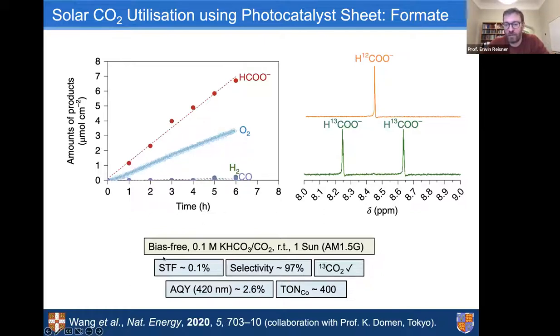The efficiency is still quite low. It sits at about 0.1%. The selectivity I mentioned is very good for formate, and the turnover number for the cobalt catalyst is about 400. Importantly, also the isotopic labeling is very clean.